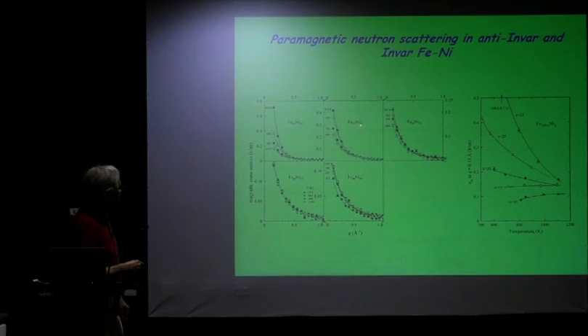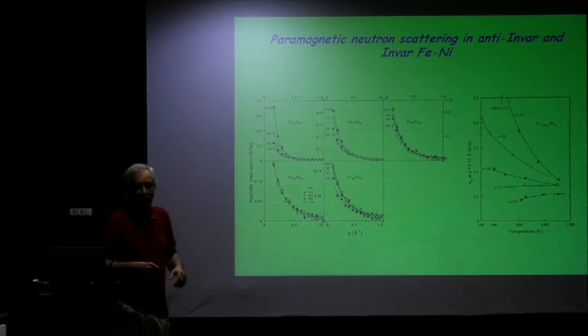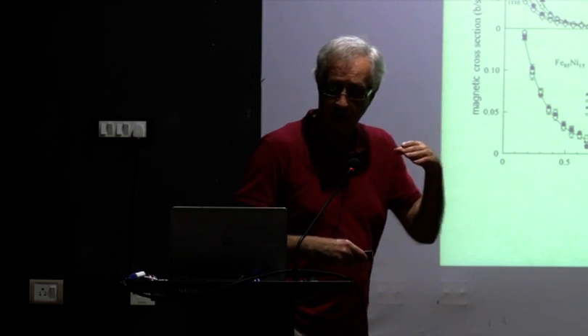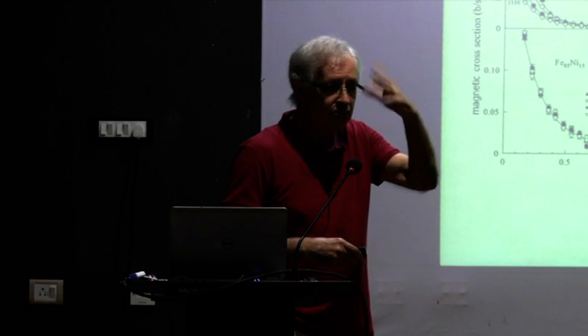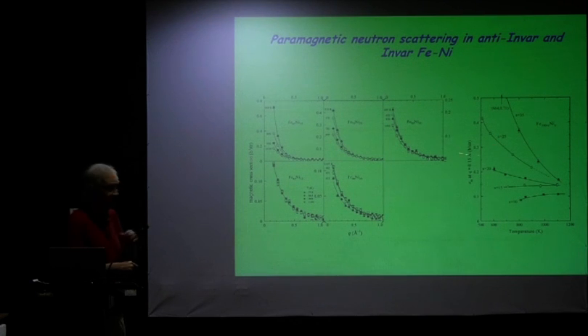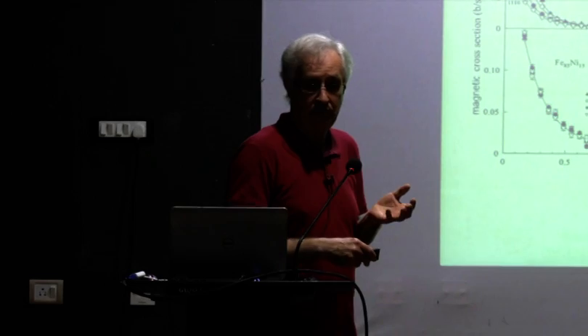You go to the next one, iron 75, nickel 25. This was the composition where the thermal expansion was crossing the general lattice curve. So you were seeing somehow both kinds of effects in that particular system, both the anti-invar and the invar effect. Again here, as you increase the temperature, the forward scattering weakens, which is an expected thing. If you estimate the magnetic moment, you see that in the x equals 35 sample it decreases with increasing temperature. Here it also decreases, and as you come to more and more iron-rich compositions, this decrease becomes weaker. At x equals 15, there's practically no change.